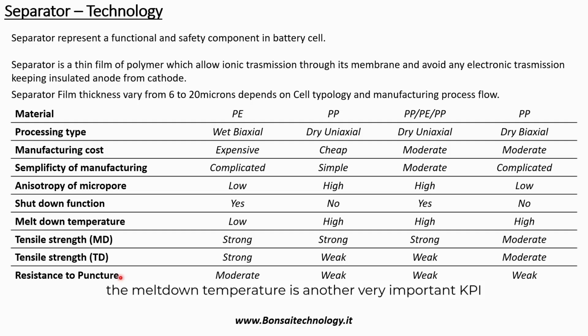To the other side, the meltdown temperature is another very important KPI, because if we have a thermal runaway temperature at, I don't know, 200 degrees, and our meltdown temperature is at 120 degrees, that means that the separator degradation will start at 120 degrees, and then we can have some failure, failure due to the shrinkage of the separator, because with the temperature, you don't know what happened to this separator.